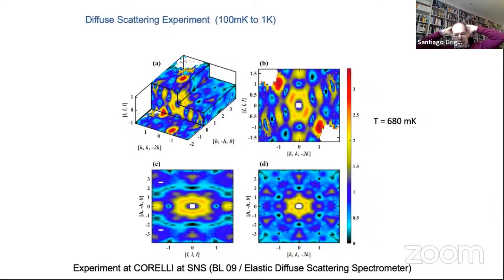And one of the nice things about current day neutron experiments is that you get a lot of data in a short time. So you can do an experiment for 4 or 5 days and you can get a terabyte of data out of that. So essentially the problem is no longer how to measure properties, but what to do with the data once you have it. So this is what I'm going to try to discuss in these last 5 minutes. So what we did then was to measure diffuse scattering for dysprosium titanate. This is the isotopic dysprosium titanate, and we chose a temperature. This is 680 milli-K, that it's low enough that we see correlations, but it's high enough that the system is not frozen.